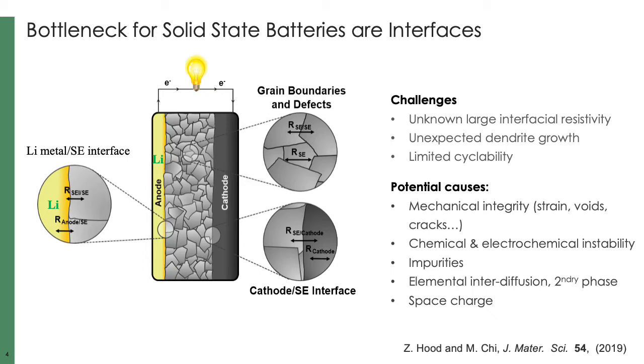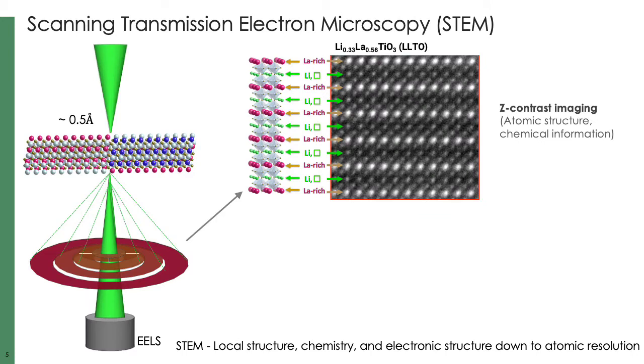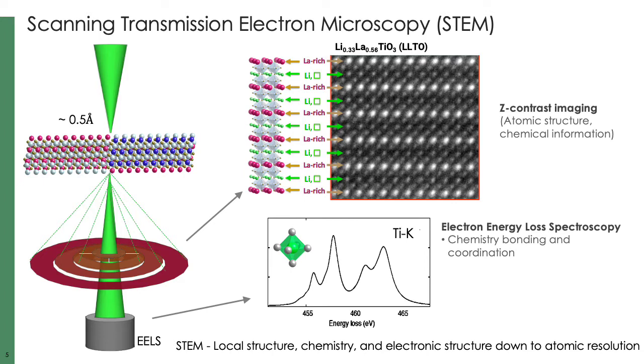Looking at local features is the strength of STEM — scanning transmission electron microscopy. The way STEM works is by rastering a tiny electron probe, which is often half an angstrom in diameter, on a specimen. We integrate electrons after they interact with the specimen utilizing annular-shaped detectors, and then you can get atomic resolution images such as what is shown on the right side. You can also put your electron beam at any atomic column you are interested in and find out the chemical species as well as bonding information. Very recently, monochromated EELS allows us to also probe optical and vibrational responses in materials.